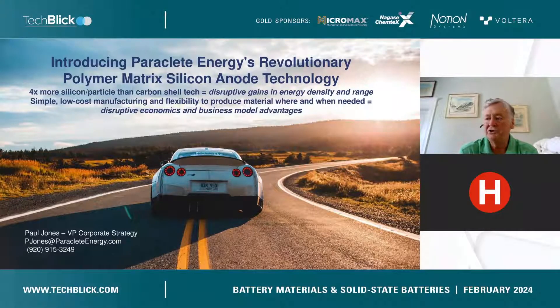But I suspect we're also familiar with the issues that make realizing that promise difficult. Silicon has better physics but reality expands — it expands as much as 400% during lithiation, and then of course it shrinks back to the starting size more or less during delithiation. That expansion-then-shrink cycle leads to very poor cycling performance for a battery in terms of cycle life and stability.